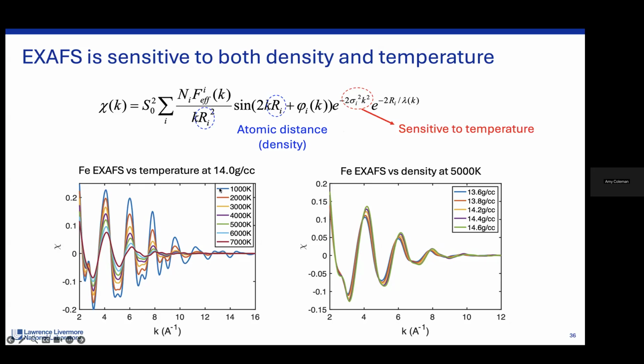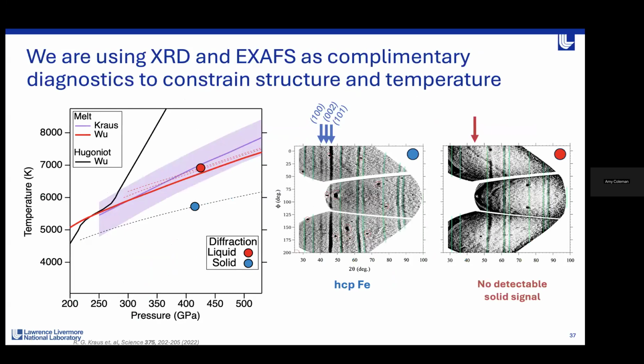On the bottom left here I've got some simulated XAFS data. At relatively low temperatures, 1000 Kelvin, we've got really high amplitude oscillations. By the time we get to 7000 Kelvin, we really drop those oscillations. So we can make XAFS measurements and use that data to infer temperature.